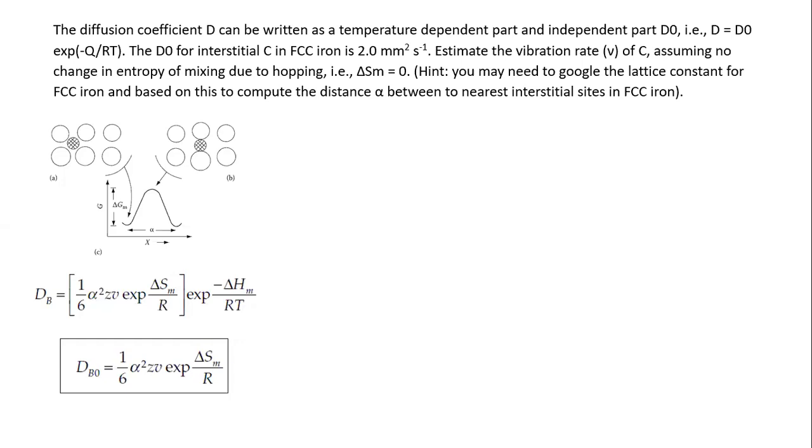But if you have corrections, you have corrections with respect to Z, right? This is going to be a function of the concentration of the atom. It's Z times 1 minus roughly the concentration times a constant. This is a first order correction. Now we're considering a 0 order approximation, thinking that the concentration is very low. Does that make sense to you?